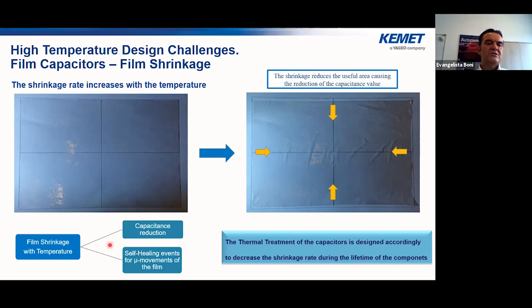During the film shrinkage, two effects can happen at the same time. One is the capacitance reduction, for the reason that we've already explained. The other is the increase in self-healing events due to the micro movement of the film. The solution adopted by KEMET was to work deeply on the thermal treatment of the capacitor in order to freeze as much as possible the mechanical movement of the film with temperature, in order to avoid further shrinkage during the working conditions.